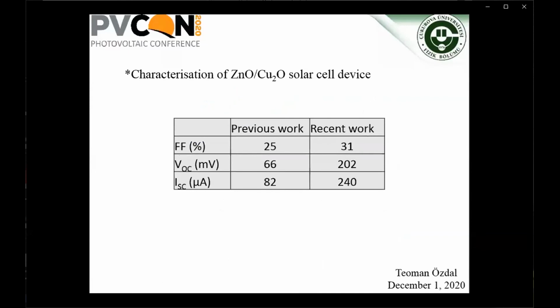Here, we can compare our recent results with our previous work. This comparison is still quite meaningful, even though it is not with the device with pure zinc oxide. Because the increase in fill factor and output voltage indicates that we have produced a better interface. The increase in the fill factor showed that we have better interface because of better crystal match between zinc oxide and cuprous oxide. Output voltage and current also increased around 3 times. These results are achieved with simple parameter optimizations in the spin coating process of zinc oxide.